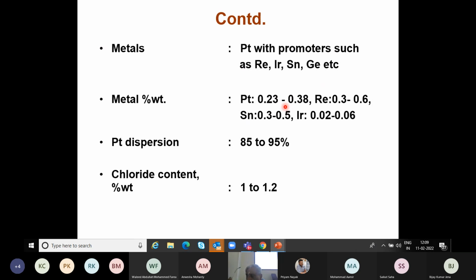And so what do we do with that platinum then? Okay, because there are several tons of catalyst, several tons of platinum sitting in that catalyst. So what we do is that this spent catalyst is analyzed several times to establish the platinum level, and then based on that, this catalyst is sold to platinum recyclers, which recover the platinum from there, and they pay you the money.